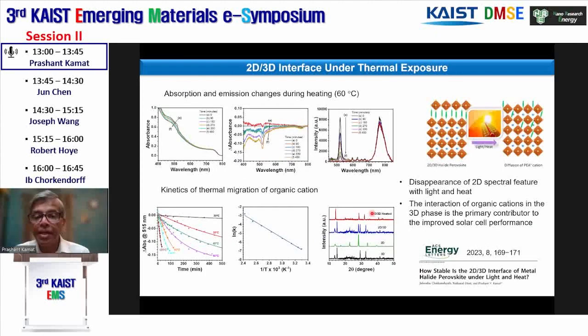So what about heating? Very same effect. You see here, this 2D peak decreasing and emission of the 2D layer decreasing. So essentially what is happening is these cations are migrating to the bulk phase, and there is no more 2D there. It could be a quasi-2D. So here it is at room temperature. You can follow the changes at different temperatures, and you can get an activation energy for this process.